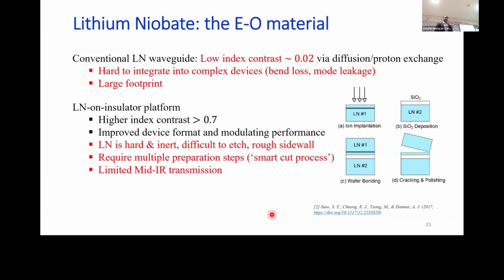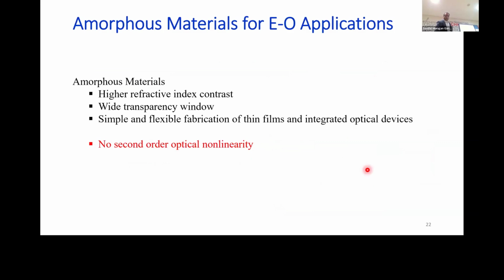But if you are working with lithium niobate, you know that it's very hard to produce integrated devices based on it because of the hardness and the directionality and all the associated properties of a crystal. There is an alternative to produce high refractive index contrast, which is lithium niobate on insulator, but it's very expensive and it introduces a lot of steps. Therefore, what we have come up with is an amorphous material platform, which is nothing but a thin film you deposit on top of any substrate, and then you apply what is called thermal poling to induce second order optical